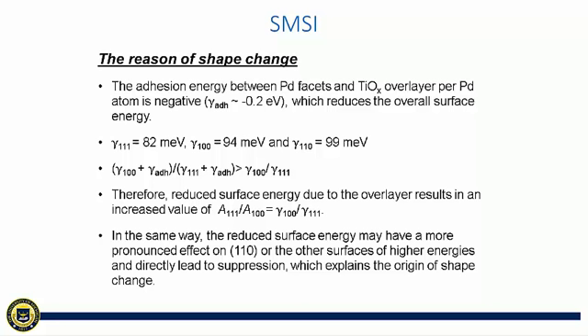First, the adhesion energy between palladium and the TiOx overlayer is negative, so the formation of the overlayer results in the reduction of the overall surface energy. And for palladium, 111 has the lowest surface energy, followed by 100 and 110.